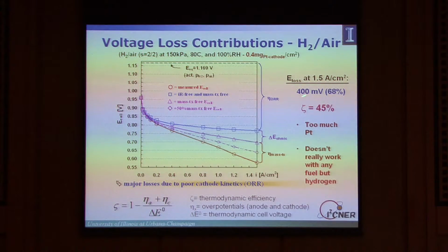Now, we can look at that drop right here, and it's very easy to convert this drop in cell voltage to a thermodynamic efficiency. And when we do, what we discover is that the thermodynamic efficiency in this best case scenario works out to be on the order of about 45% or so. And so that's not nearly what we think we can get thermodynamically out of a fuel cell.